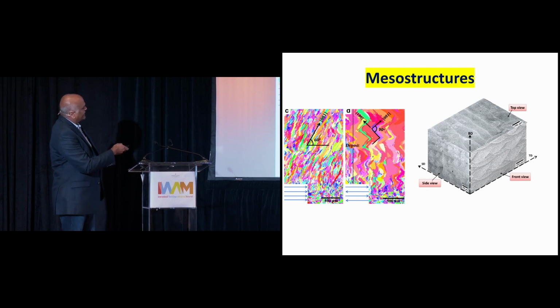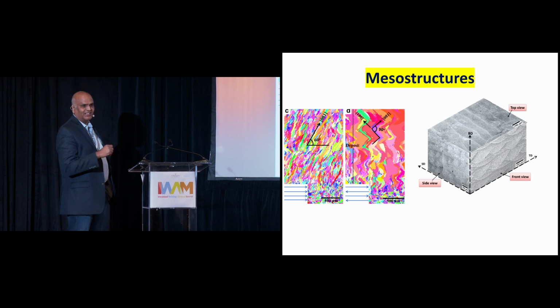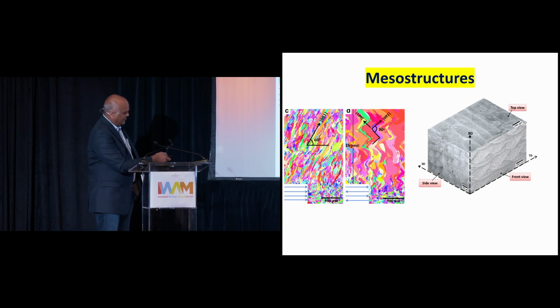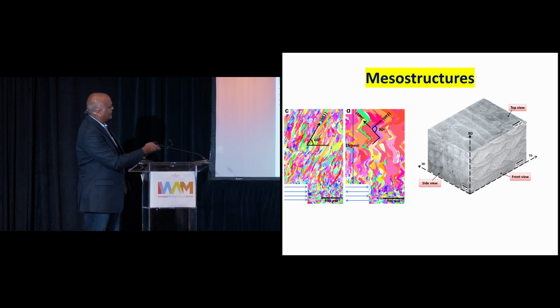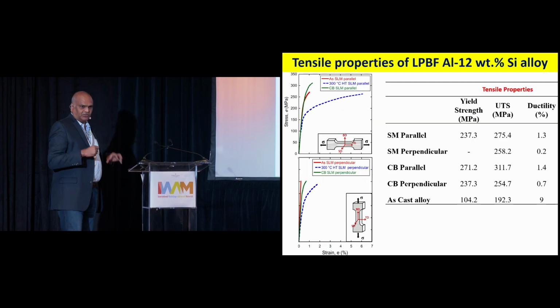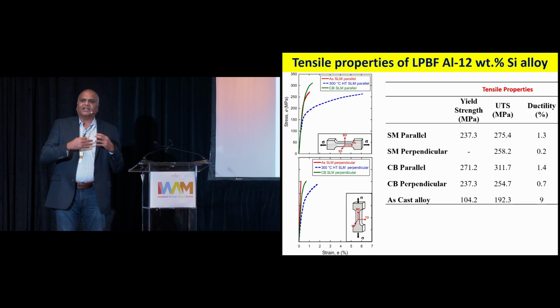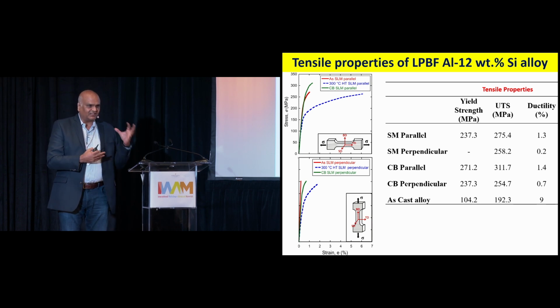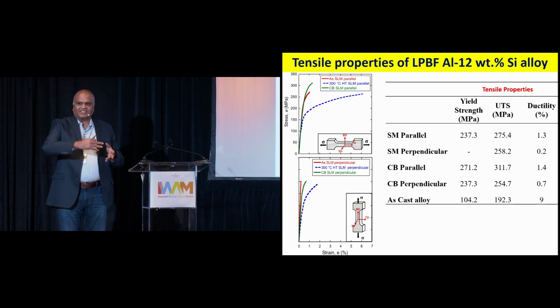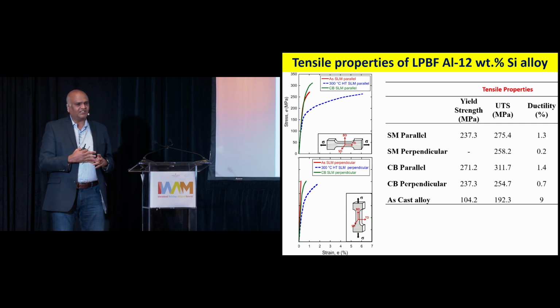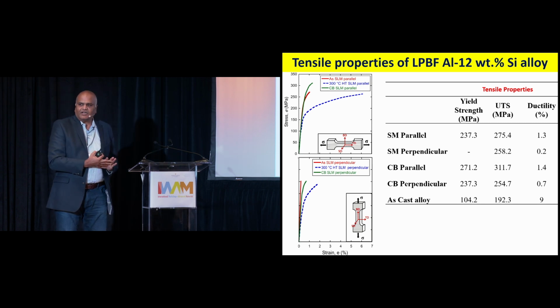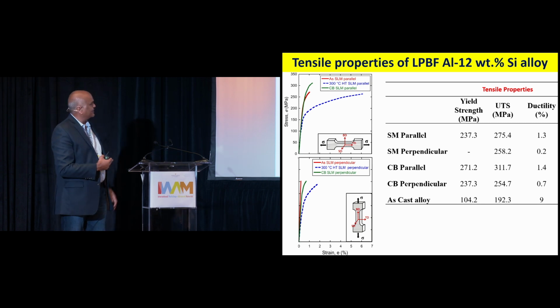On the other hand, if you change to the anti-parallel direction in alternate layers, you get this zigzag kind of fashion. So you can actually engineer these meso-structures, whose signatures will be left like this. That just tells you the kind of microstructures that are possible—submicron scale, micron scale, and mesoscale microstructural features—and they will all obviously influence the mechanical properties.